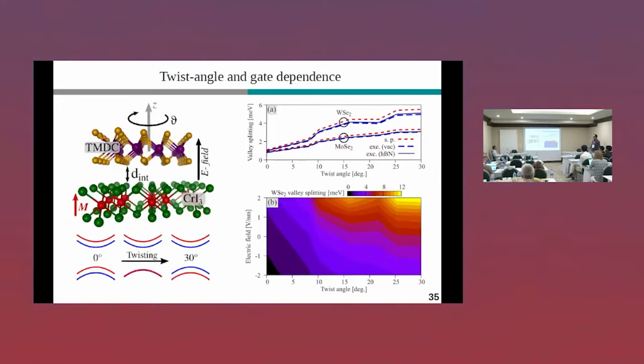And this has profound consequences for the valley splitting. So the most important result is here. This is the calculated valley splitting for tungsten diselenide on top of monolayer chromium triiodide when we twist and gate. And the tunability is really giant. So you can go from 0 to 12 millielectron volts in the valley splitting by twisting and gating. These 12 millielectron volts correspond to an external magnetic field of 60 Tesla. And this is really a gigantic field.